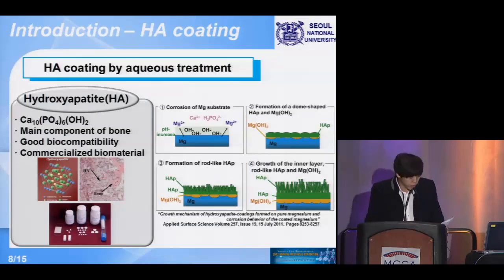And as I mentioned before, corrosion is one of the biggest problems of magnesium. Because porous magnesium has a much larger surface area than dense magnesium, the corrosion occurs much faster. So we tried to apply a hydroxyapatite coating by the aqueous treatment introduced by Hiromoto's group.